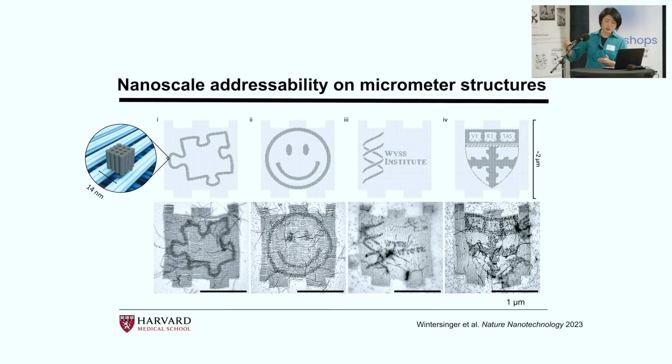Using crisscross, the lab has created some of the largest fully addressable DNA origamis to date, and crisscross also has this built-in resolution of 14 nanometers, so you can see in the top left corner there. On this origami surface, you can put any 2D pattern that you would like, and those patterns can then later be functionalized with antibodies, carbon nanotubes, anything that you can put an oligonucleotide handle onto. In this particular example, we've used DNA again, so it's a DNA nanocube that is decorating the surface. I think this makes crisscross a very versatile scaffolding for applications that might require micrometer registration.